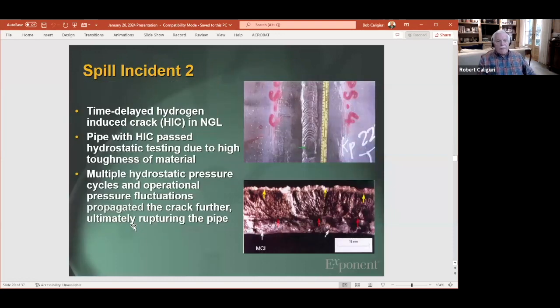This was different. This was time-delayed hydrogen-induced cracking in this pipe. And if you look, the pipe had passed hydrostatic testing; it was pretty tough steel. So it actually passed its hydro test. But multiple hydrostatic pressure cycles and operational pressure fluctuations propagated this crack. The red arrows are where the crack was initially due to hydrogen-induced cracking during the welding process. Then that crack just grew with time due to hydrostatic testing and just fluctuations in pressure, which I've seen many times now in pipeline systems.